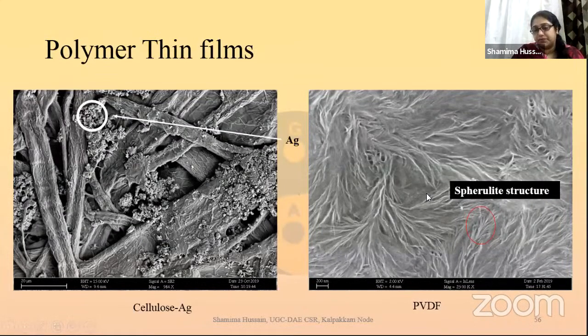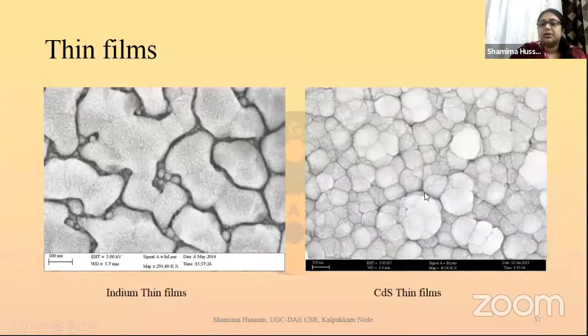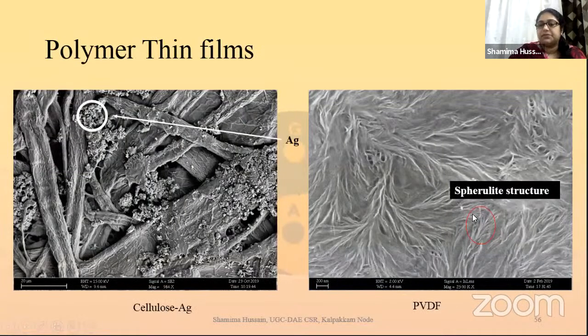And on this side I have a polymer film, PVDF, where I could see the spherulite structures of the PVDF, which are very characteristic. And see, this is what we mentioned. In any micrograph, these are the features we look for. This is called the scale, 200 nanometer, which means I could measure and say what is the dimension of this particular spherulite feature, the branch that I see. EHT is the acceleration voltage. So I've used 2 kilovolt here for my polymer because polymer is a very degrading kind of material, it will just damage itself. So we do not use high voltage here.